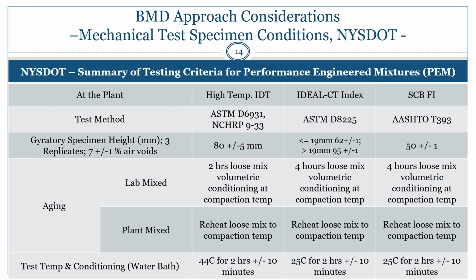depending on nominal aggregate size to make sure that there's not going to be an issue of compaction, and also the different levels of conditioning they want their mixes to be conditioned for, whether it's a lab mix design or plant produced, and also the test temperature for these tests and how much conditioning. It's important that a state agency describes this very well and clear so that industry can follow and results between the two groups can be repeatable.